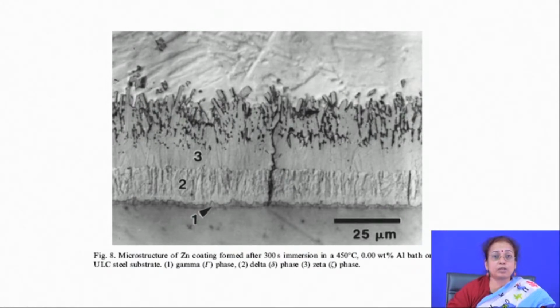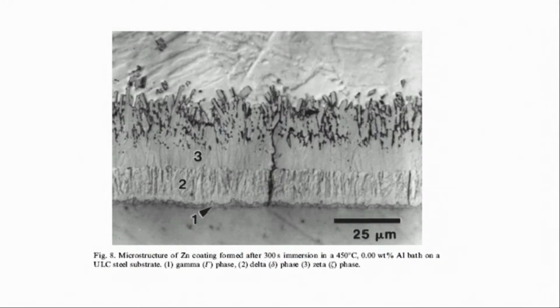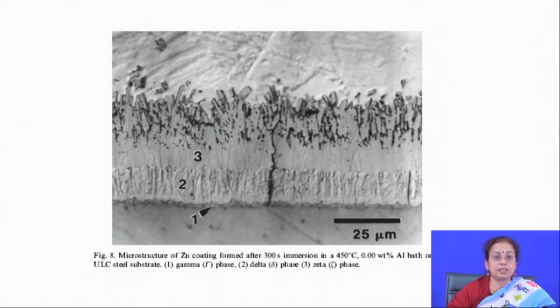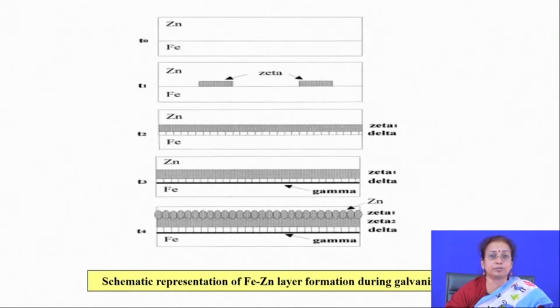So, when you talk about saving the component in a proper way, you have to look for different ways to combat this kind of intermetallic formation. Usually people go for alloying with aluminum, they also go for alloying with different other metals, in order to reduce the kinetics of the iron zinc intermetallic formation. They also go for an annealing operation to homogenize the microstructure.